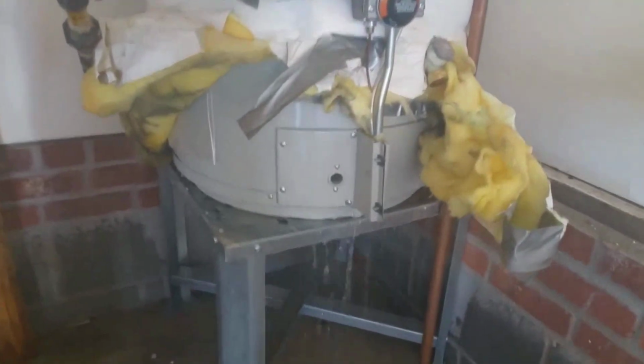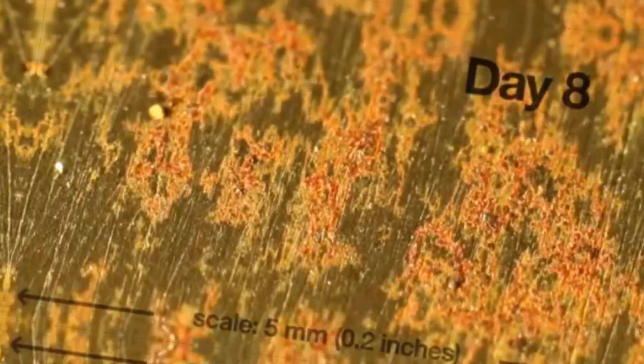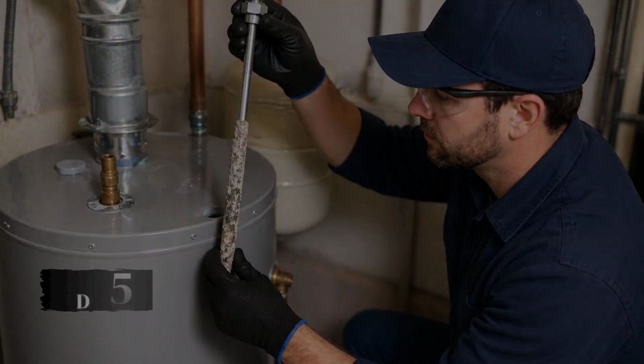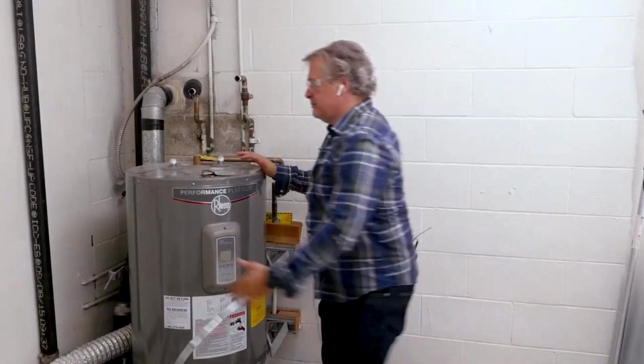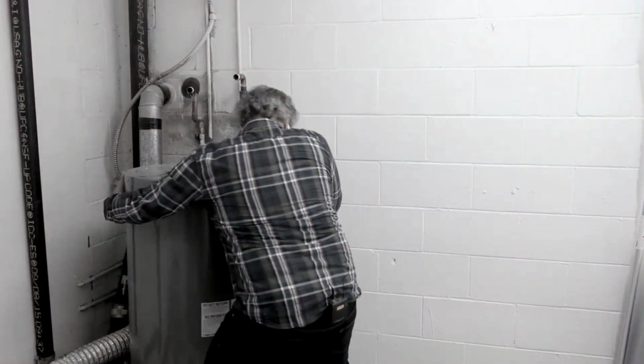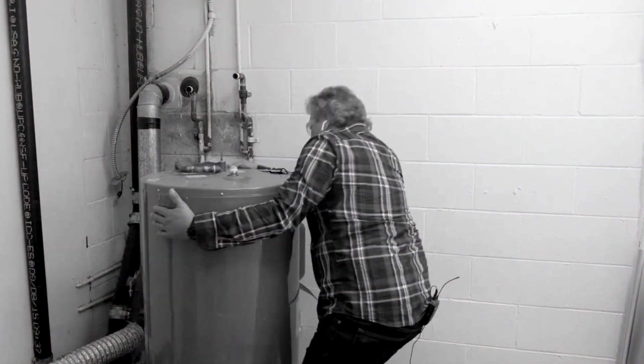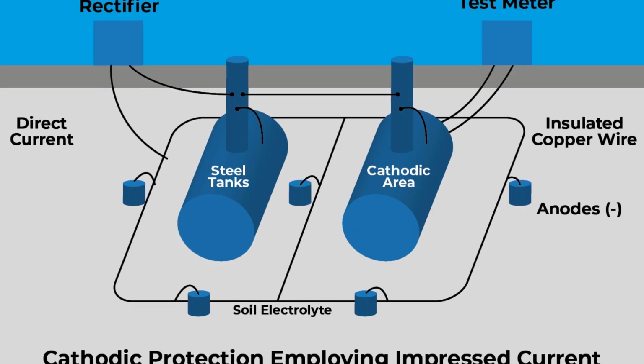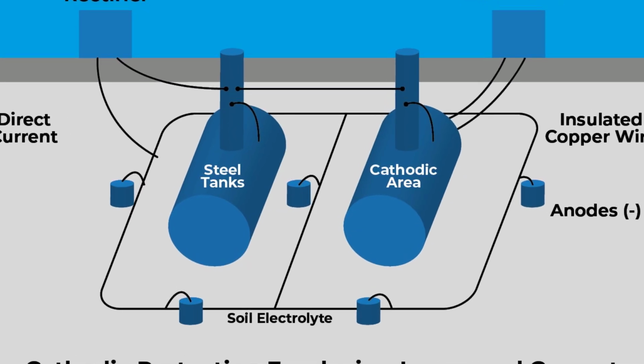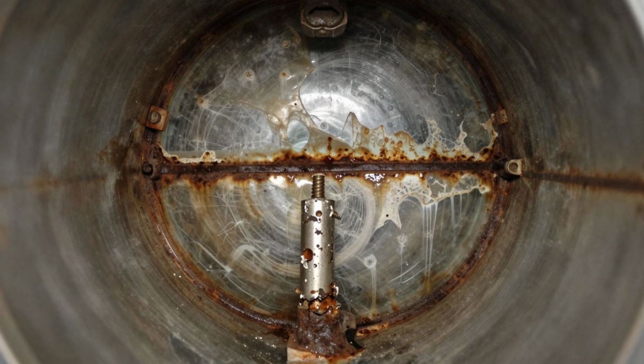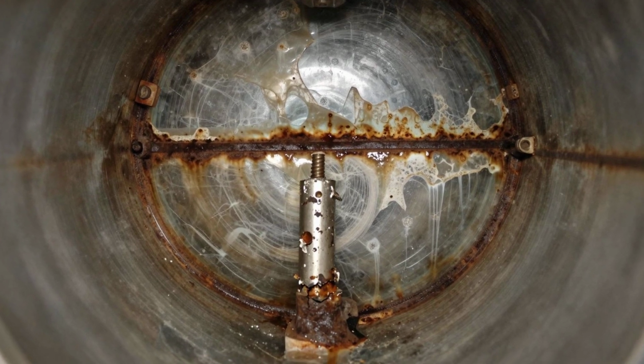Once the rod is spent, the fractured glass lining cannot hold back water and oxygen. Corrosion starts almost at once. Replacing the rod costs about $30 and half an hour of work. Replacing a corroded tank after the rod and lining have failed can cost $4,000 or more. The difference comes down to whether the protective circuit is kept intact or allowed to fail.